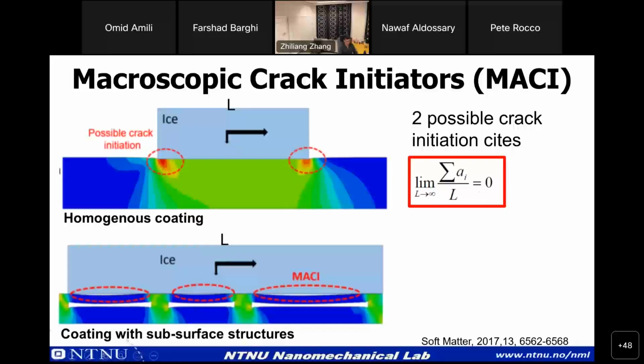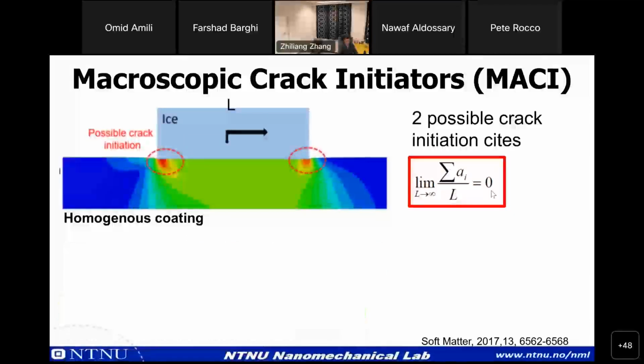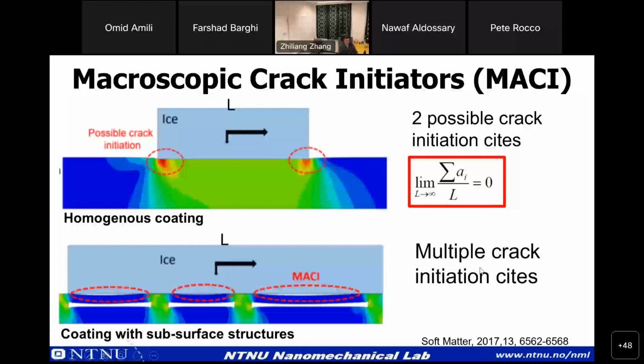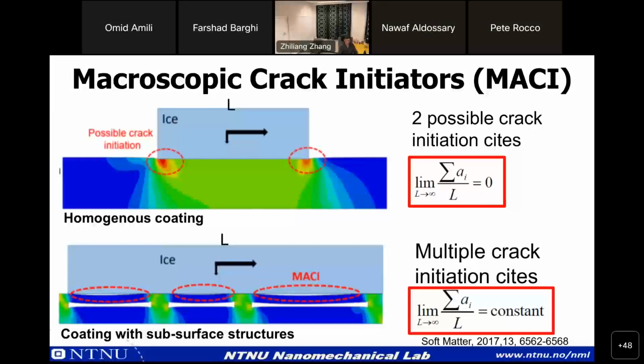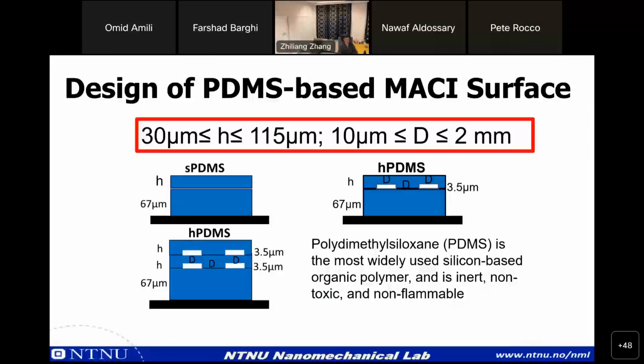However, if we do something with subsurface structures, we have multiple crack initiation sites. If we take the limit, the total crack length over the ice length will be constant. You see, this is the difference between the case with MACI and without MACI. Now we have the theory. We want to prove our theory. So we choose the PDMS and try to fabricate MACI surface.